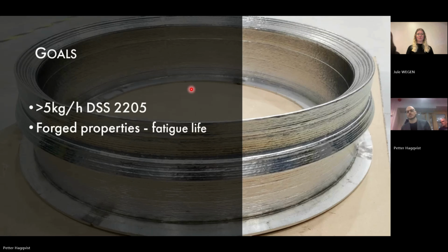So the goals that we set up in this project was that we were to reach a deposition rate of 5 kilos per hour of duplex stainless steel. 2205 was the target material. We were also getting into other alloys, which might be discussed by some other speakers later today. And the goal was also to get forged properties. And that is primarily determined by the fatigue life of the part. So the dimensioning requirements for the material is not static properties, but fatigue properties, which makes it much harder in terms of building this material.